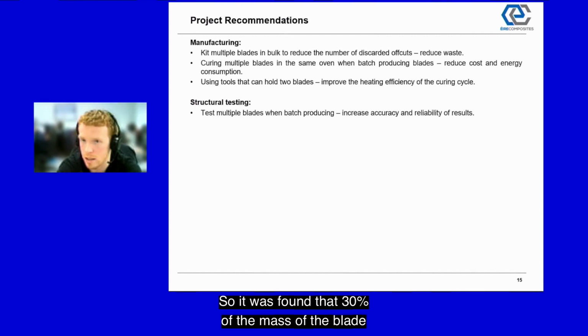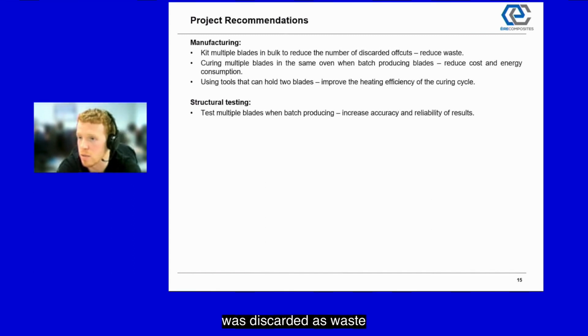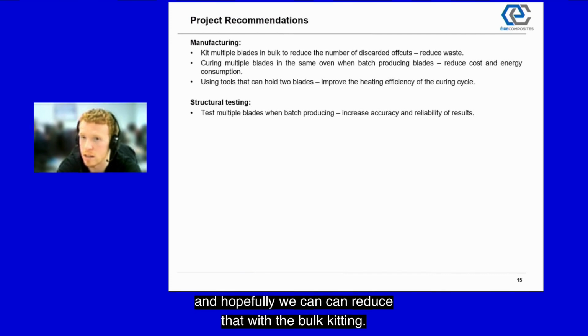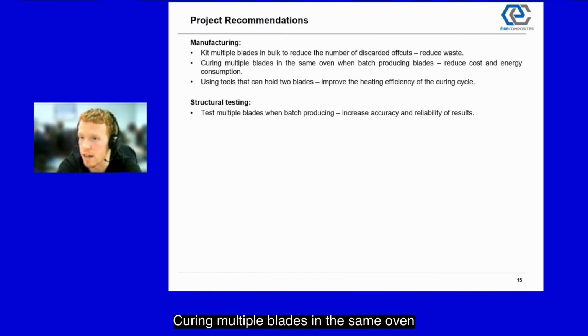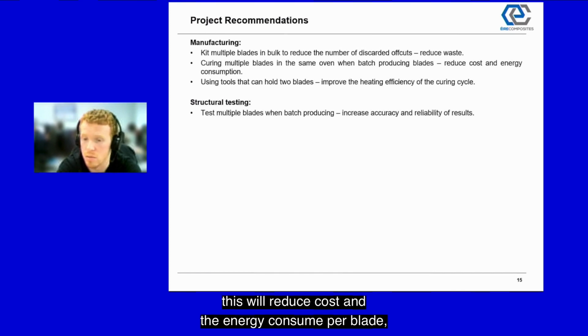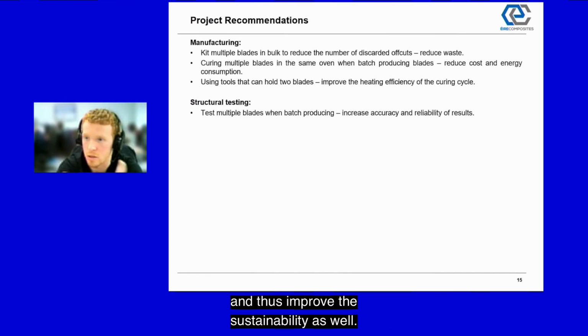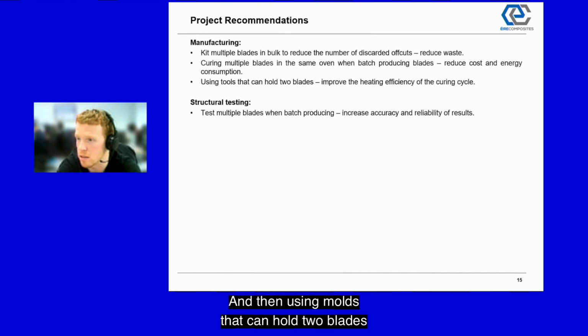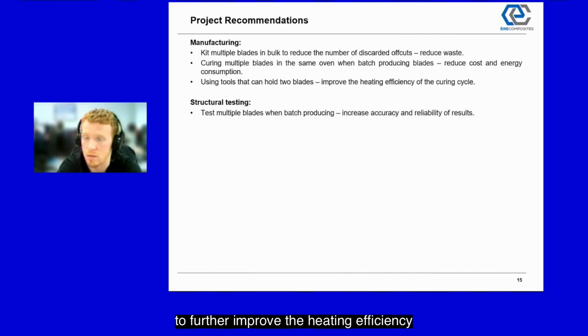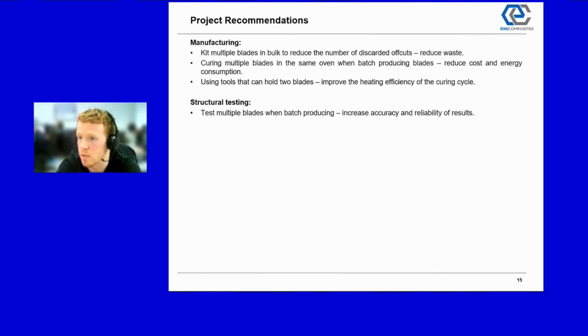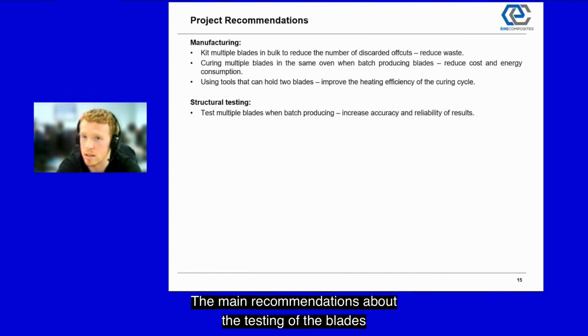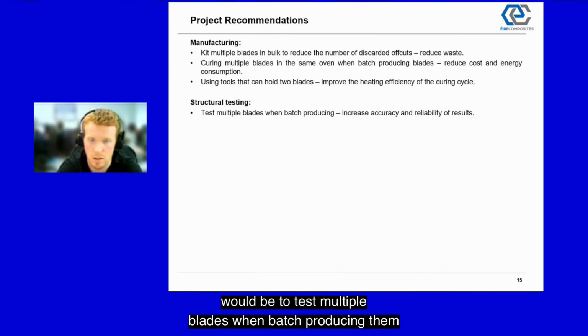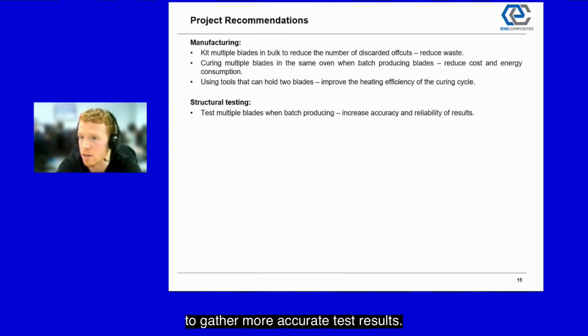It was found that 30% of the mass of the blade was discarded as waste, and hopefully we can reduce that with the bulk kitting. Curing multiple blades in the same oven when batch producing blades will reduce cost and the energy consumed per blade, and thus improve its sustainability as well. And then using molds that can hold 2 blades would further improve the heating efficiency of the curing cycle. The main recommendation about the testing of the blades would be to test multiple blades when batch producing them, to gather more accurate test results.